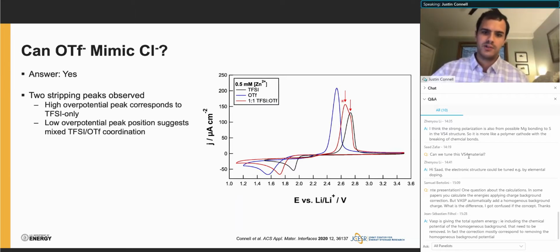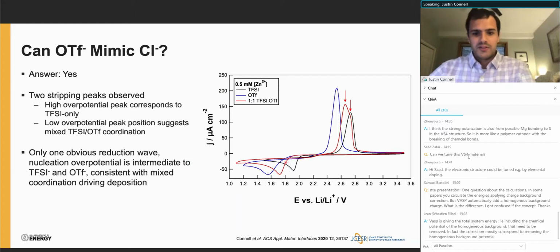But this lower potential peak sits directly in between the 2, the triflate only and the TFSI only, suggesting that there is mixed TFSI triflate coordination in the system, in some contrast to what appeared to be distinct populations in the TFSI chloride system. We also see only 1 obvious reduction wave, which is again consistent with mixed coordination driving deposition, and the location of this peak is again directly intermediate to the triflate only and TFSI only cases.